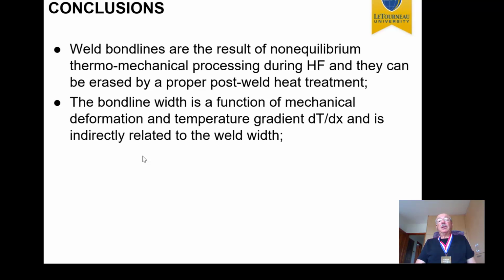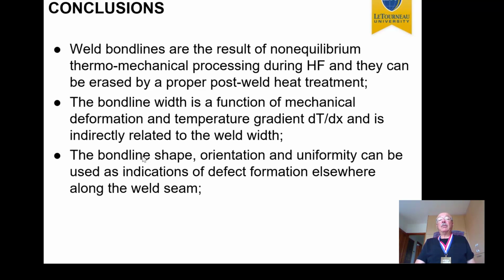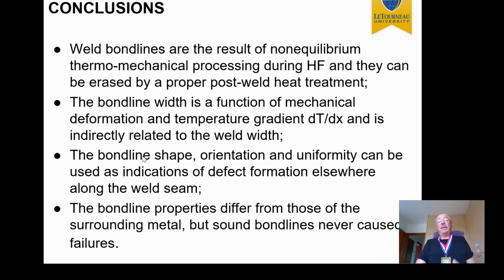and can be erased. And their width is a function of mechanical deformation and temperature, really, and they are indirectly related to the weld width, so we shouldn't be concerned that much about bond line width. The bond line shape, orientation, and uniformity, on the other hand, are important, and we can use them to indicate defect formation elsewhere along the seam, but the bond lines never failed. And this is the main message of my talk. After many, many years of being involved with the subject, I've never seen a bond line fail.